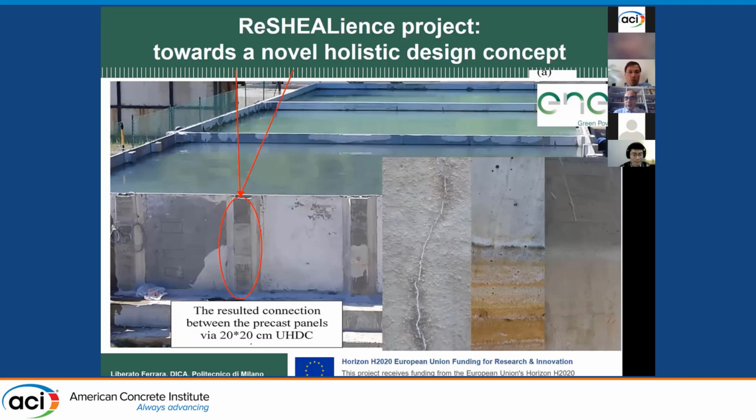These are basins cooling the geothermal water which comes from the geothermal pits. It's full up to about 1.4 meters. And you can see that we had evidence of healing of some shrinkage cracks that formed. The other important thing for us, this water contains a lot of sulfates. So the problem is the degradation of the concrete itself. And you can see in the pictures on the left an image of ordinary reinforced concrete after about 10 months of exposure to this water. The matrix is already corroding, whereas the rightmost figure is our UHDC material, ultra high durability concrete as we call it, and it's practically intact, but for the change of color where the water was there.